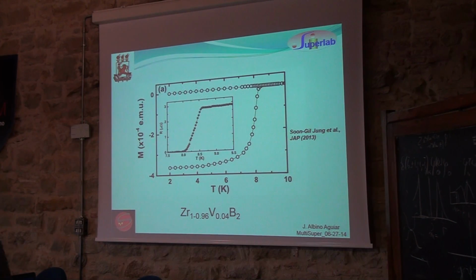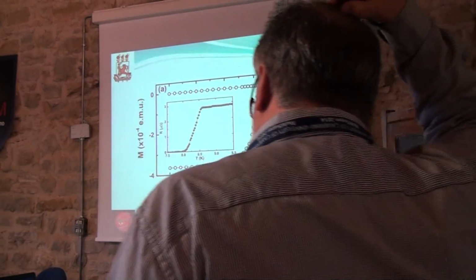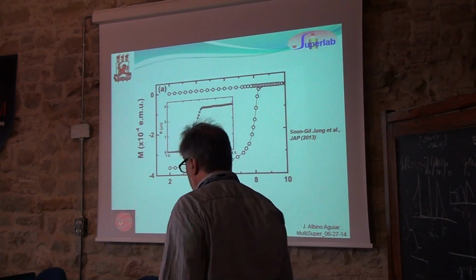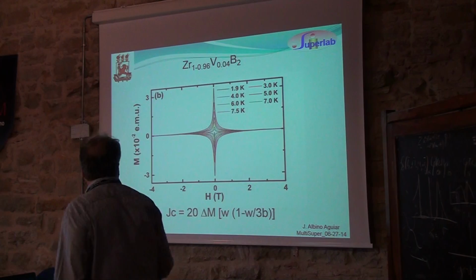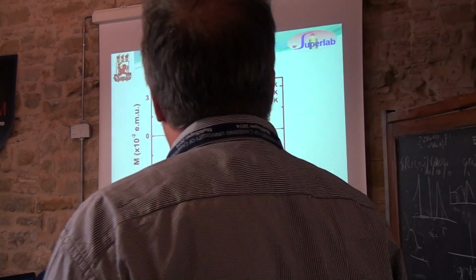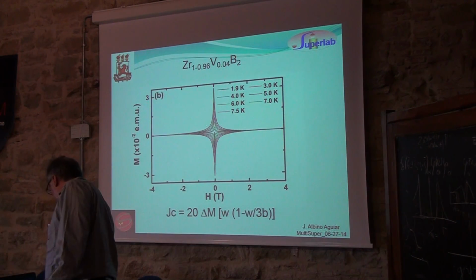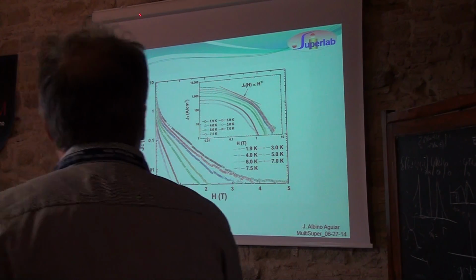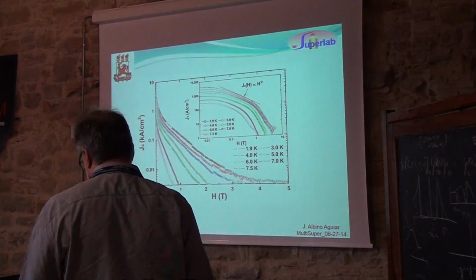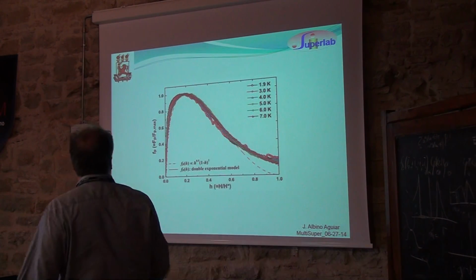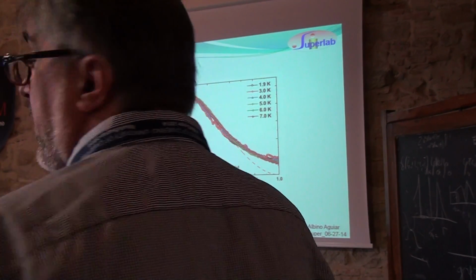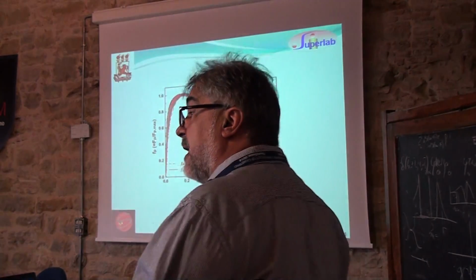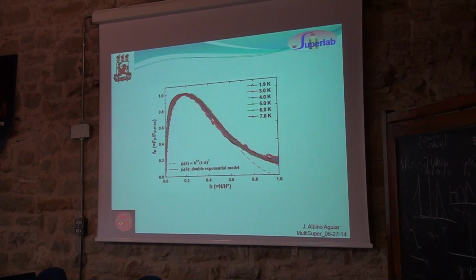And we have also done some Jc, critical current measurements. This was published in this article. So again, you make these curves, you take delta M and use the Bean model. W and B are the sample parameters. And we can see that we can fit an exponential, and you can calculate the pinning force, and you see that it fits well with a double exponential method, indicating that indeed we need two bands. Of course, I'm not proving that it's a two band.